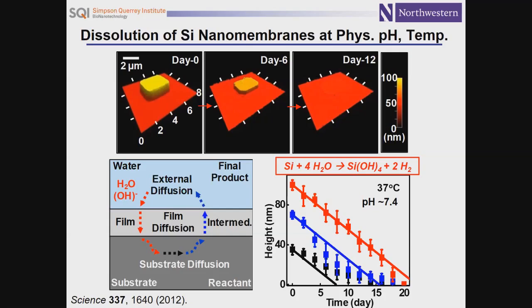This is a very poorly appreciated fact — not really apparent when you're dealing with silicon in wafer form, where the thickness might be a millimeter or half millimeter. But if you're interested in these nanoscale forms of silicon, as I mentioned before, due to their interesting mechanical properties, you quickly realize through experimental studies that silicon actually does dissolve in water at physiological conditions at a very well-controlled rate. This is defined by surface erosion processes where the reaction involves the hydrolysis of silicon to form silicic acid, at rates of a few nanometers per day in terms of change in thickness.